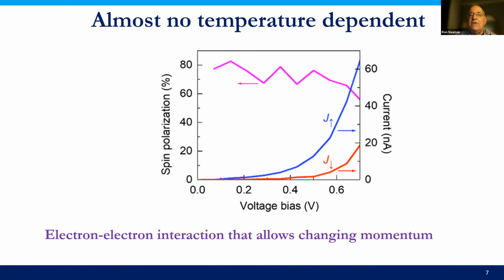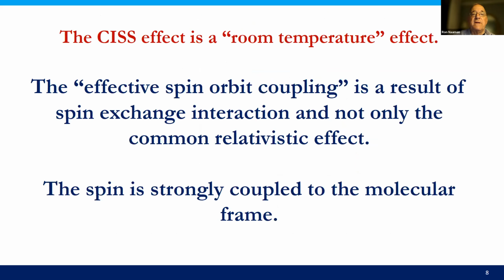So what you realize is that an electron going through a chiral molecule must interact with the molecular system. So it couples the linear momentum with the molecular system, and this is the essence of the CISS effect. As a result of it, the CISS effect is a room temperature effect. Not like regular spintronics, where we prefer to work at low temperature in order to get good results. The CISS effect, because it involves vibrations and interactions that enhance the effective spin-orbit coupling, and I'm not going into the discussion here, but there are now theoretical papers by several groups, both in the US and in Europe, that calculated that this interaction is enhanced by temperature, and as a result, the effect is a room temperature effect. It persists at room temperature.